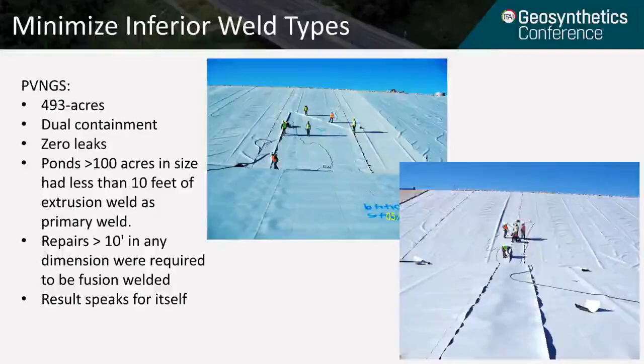Technical specifications should minimize inferior weld types. There's different ways to do that. One is picking a length where that length cannot be exceeded in repair. And if it is, you have to use the primary welding method, for instance, extrusion versus fusion. If you do that, the results speak for themselves. You can really minimize the amount of inferior welding that's out there if it's just planned for and addressed.